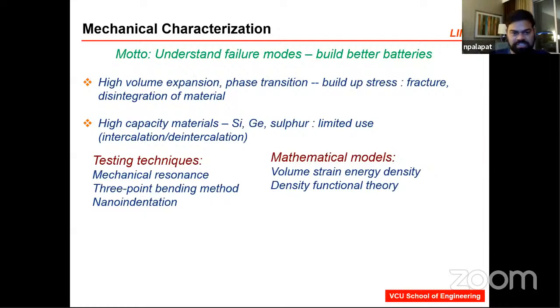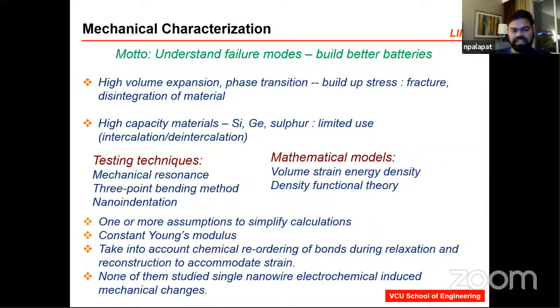Now, though there is a lot of research ongoing, there are quite a few drawbacks in all these techniques. For example, if they are studying using a three-point bending method, in the experimental setup, the nanowire is not hanging as a bridge like what I showed in my experimental setup. They lay flat on a surface and you do a three-point bending on that. So the measurement is not accurate given that these nanowires are really, really small in diameter. And moreover, in the mathematical models, as you all experience, you give some known parameters, you fix some of them as constants, and then you try to calculate something else. So the measurements themselves are not really accurate. They don't give the real information of a nanowire.